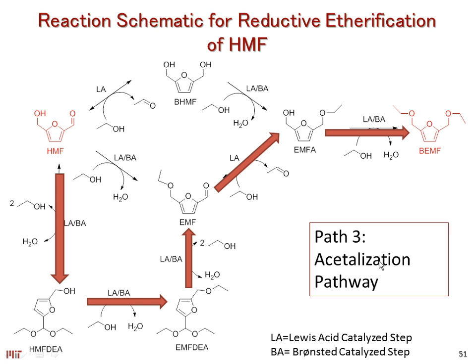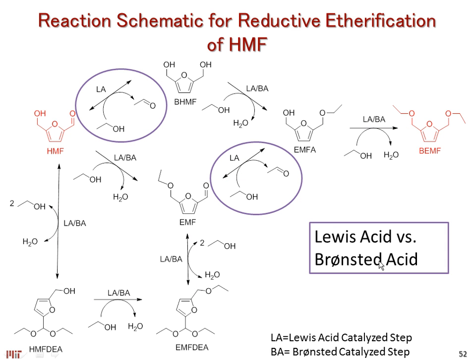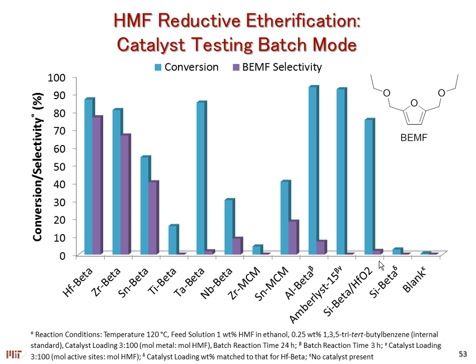We know now that actually this pathway is very unfavorable, and usually you go back through here. But what I wanted to show you is, again, we can now couple this with an alcohol, a primary alcohol, a secondary alcohol, and do this transfer hydrogenation chemistry and start coupling these two steps over here. So again, similar methodology. We do the screening with our materials.